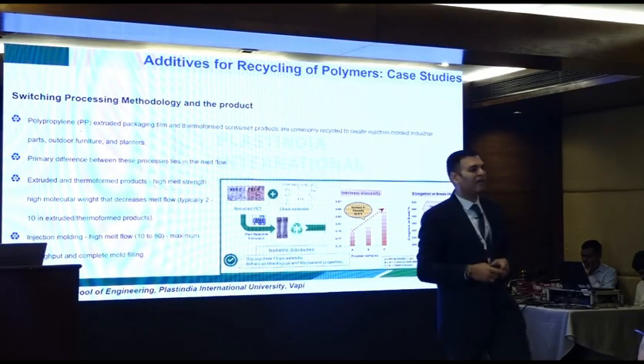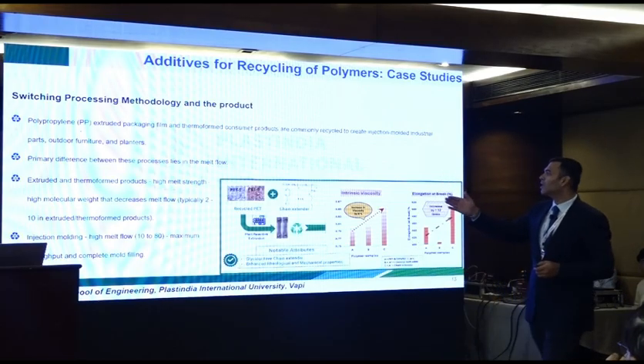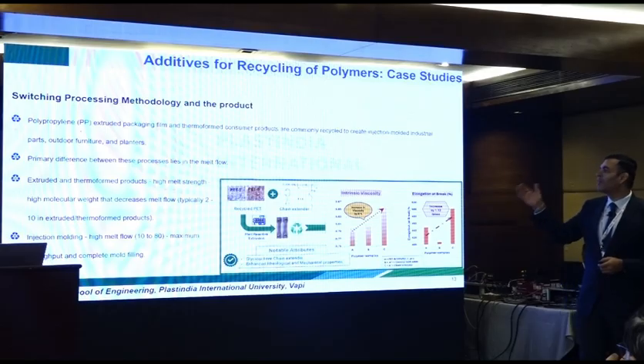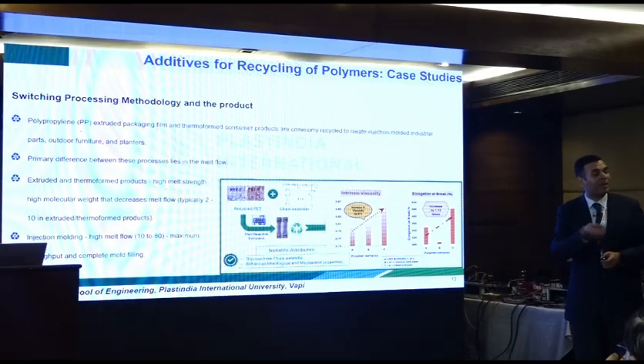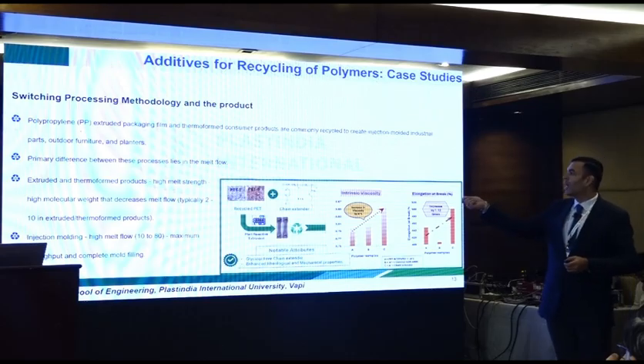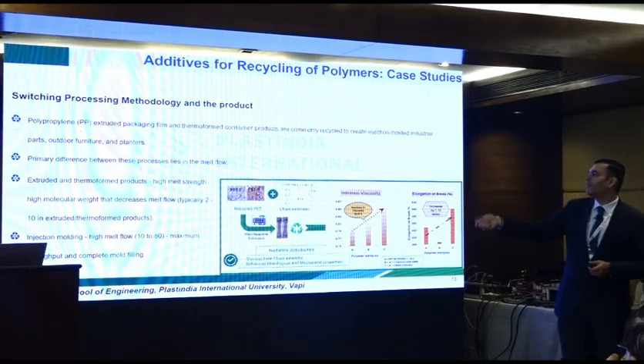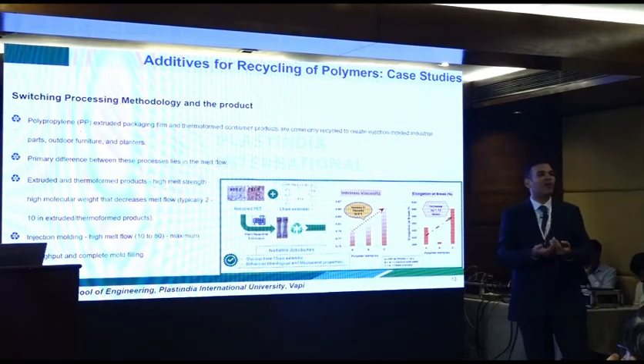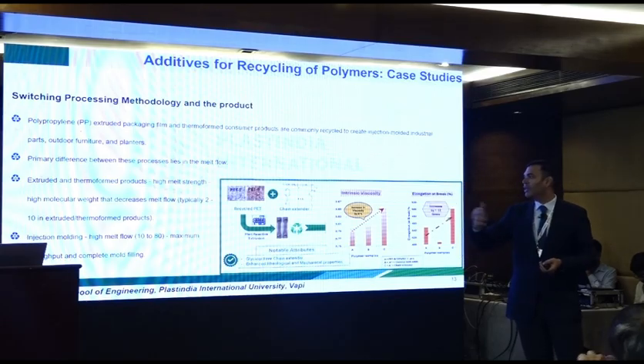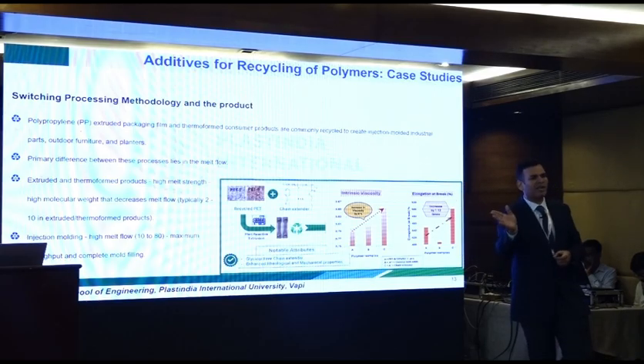even if it is CH2 CH3, which is propylene and polypropylene eventually. So extruded and thermoformed products, you require high melt strength, strand बनना चाहिए, preform बनना चाहिए. So you require high melt strength and high molecular weight that reduces the flow of the product. Typically 2 to 10 in an extruded or a thermoformed product. It can be slightly on the lower side as well. It can be up to 5 or 6 as well.